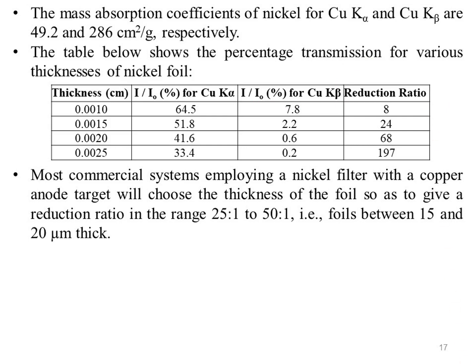It can be seen from the table that the optimum thickness has to be a compromise between reducing the intensity of the unwanted copper K beta and reducing the intensity of the desired copper K alpha.